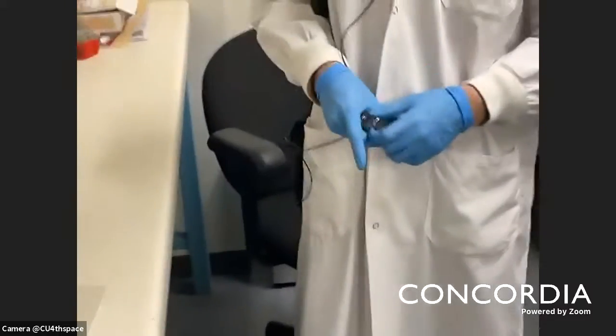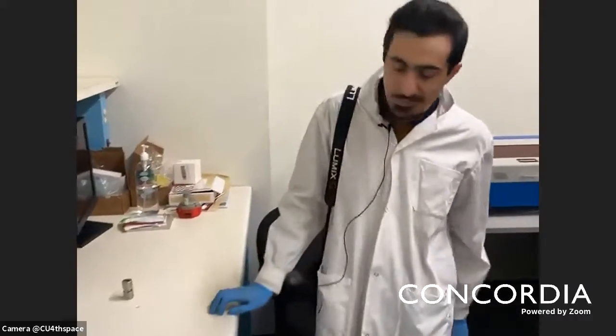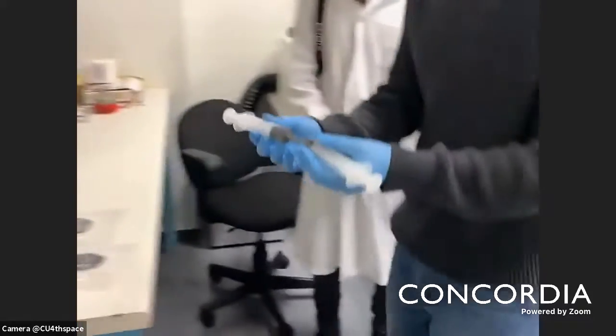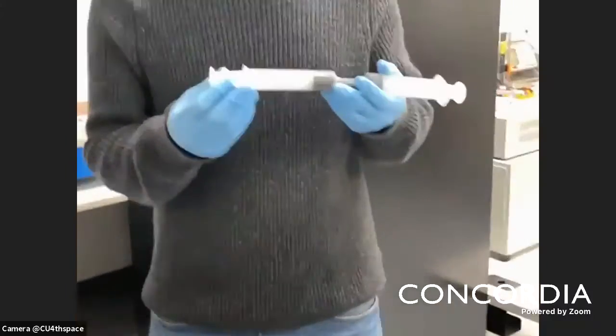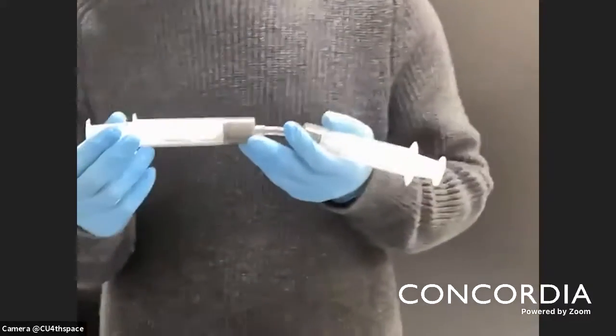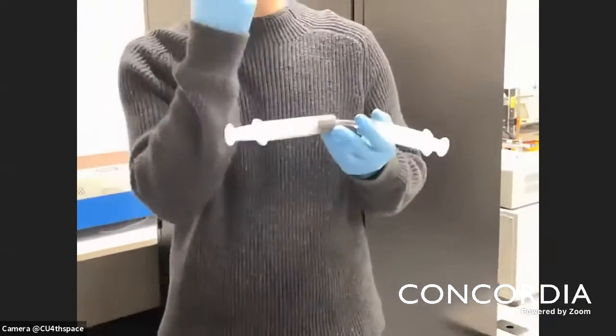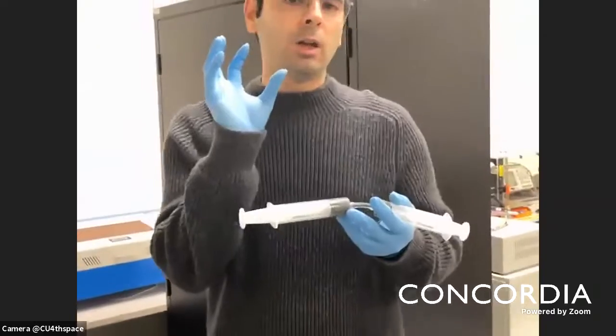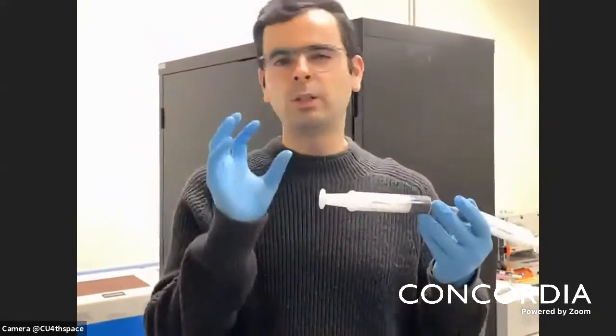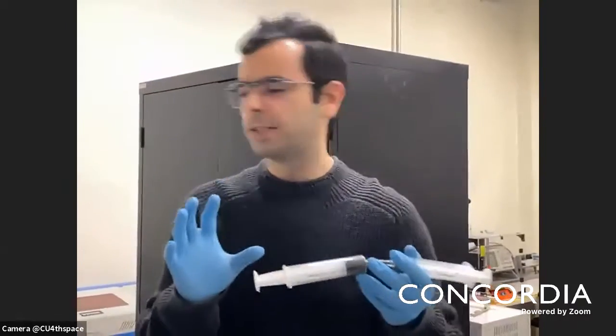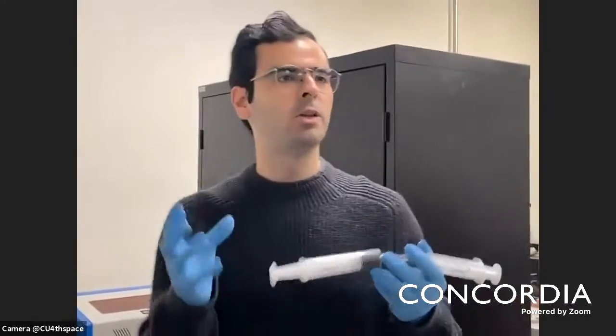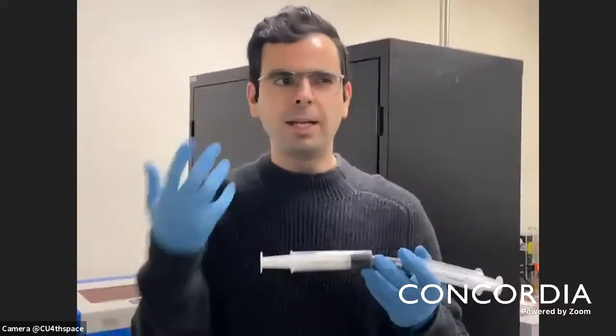This kind of material can be used in a vibration isolator and so on, if you want. So just one comment toward this fluid. Basically, MR stands for magneto-rheological. Rheology is the science of deformation, as you know, and this type of material has two main parts. One is tiny iron particles, usually with diameters ranging between 1 to 10 micrometers, and the second part is the carrier, a non-magnetic medium that doesn't respond to the magnetic field, unlike the iron powders. When we mix the two, carrier fluid and iron, we have MR material.